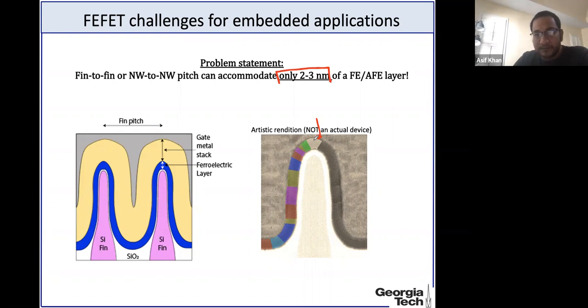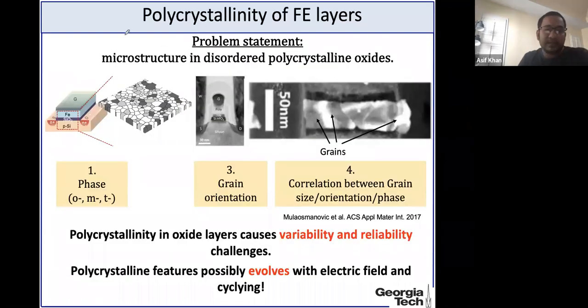So these are questions. Now, specific to this question that we mentioned in the earlier slide is that of polycrystallinity. So what does it mean? It means that whenever we have a ferroelectric layer on a transistor structure, it is sitting on an amorphous layer. So there is no epitaxial template that can make this layer a single crystal. Essentially, it's a polycrystalline material. In these ferroelectrics and anti-ferroelectrics, the typical grain size is of the order of 10 to 30 nanometers of geometric mean. And the range is probably 10 nanometers to 90 nanometers.